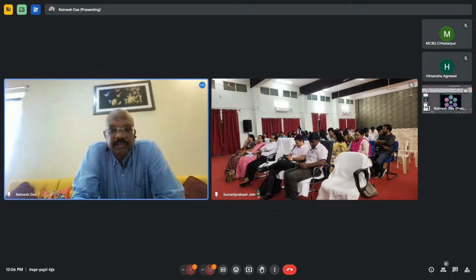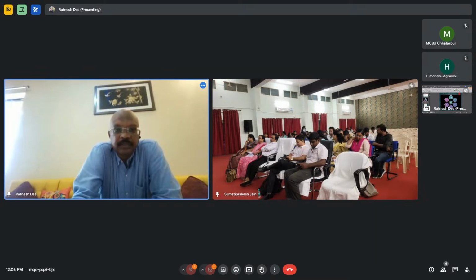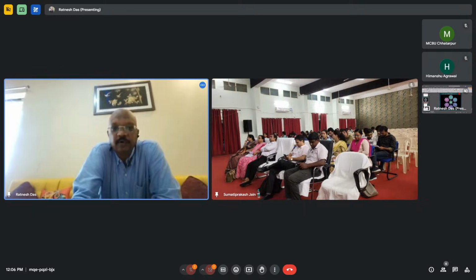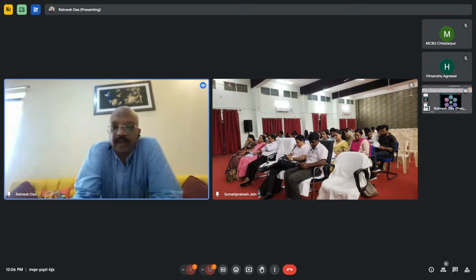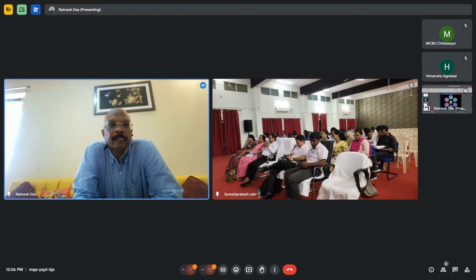Here you can see the black dots. This is the bare carbon paste electrode. The red dots are for multi-functionalized carbon nanotubes with carbon paste electrode. And the last, green one is silver nanoparticle functionalized multi-walled carbon nanotube with copper nanoparticle and carbon paste electrode.